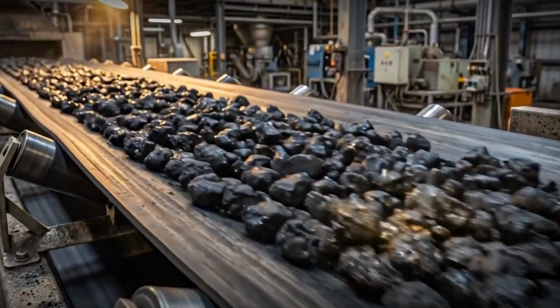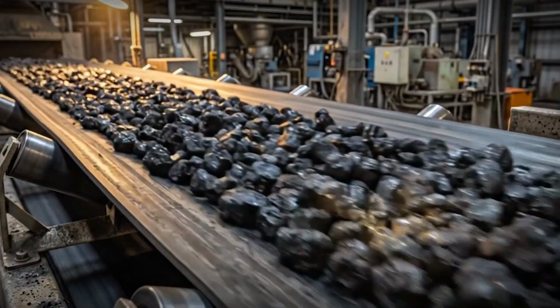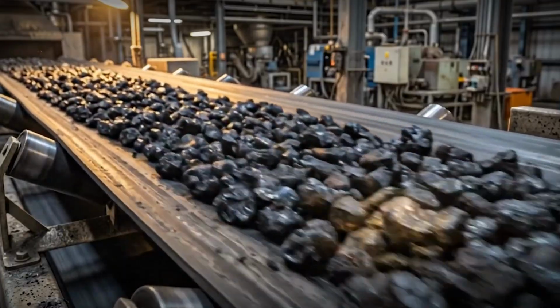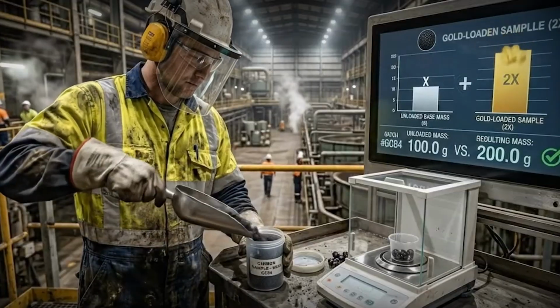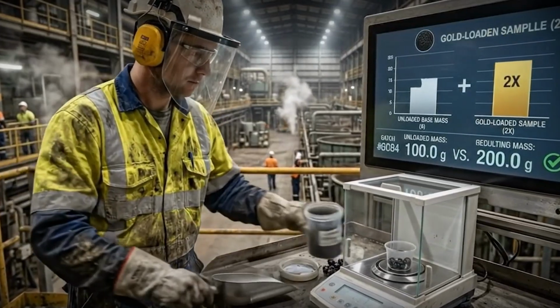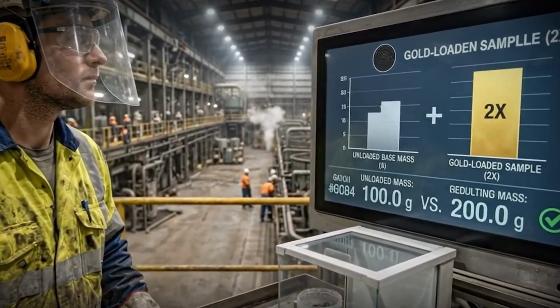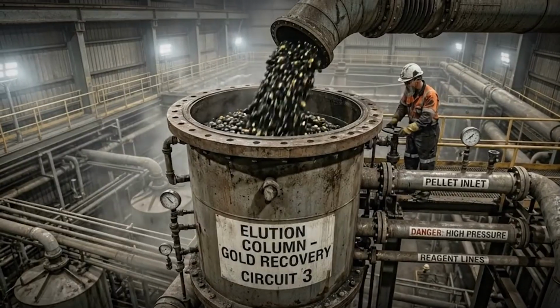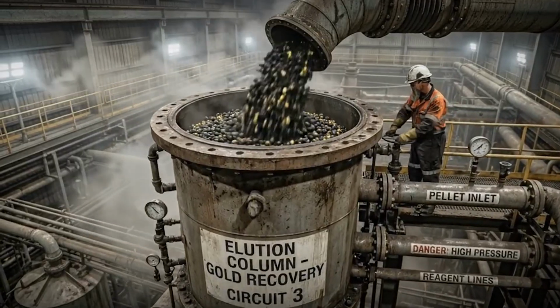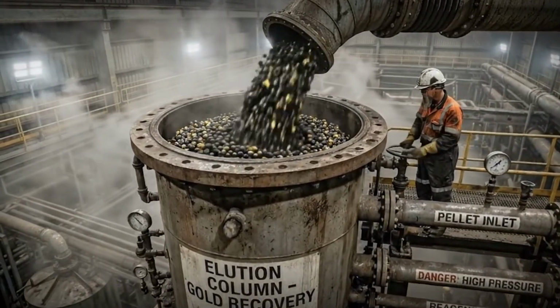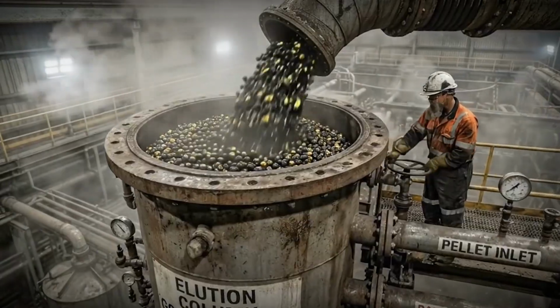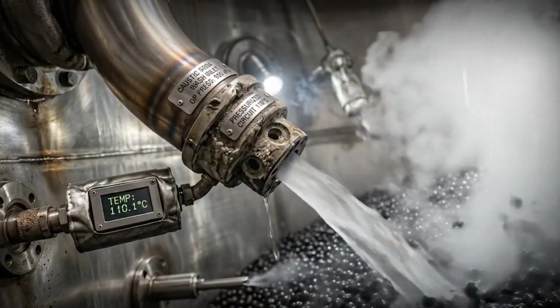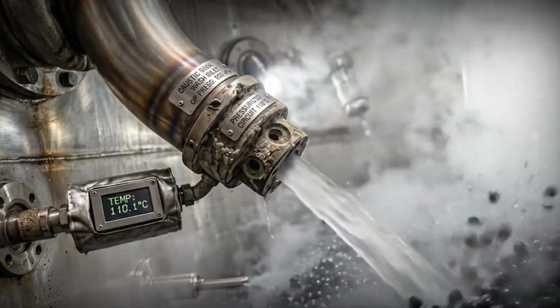The powdered ore slurry flows into a series of large leach tanks, typically 6 or more in sequence. A dilute sodium cyanide solution is added, along with lime to control pH and oxygen to accelerate the reaction. Over 24 to 48 hours of continuous agitation, the cyanide forms a chemical bond specifically with gold and silver, dissolving them out of the solid rock particles and into the liquid solution. The rock stays behind, the gold moves into the water.